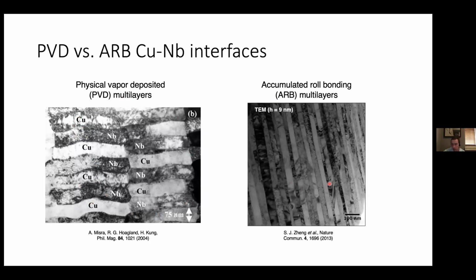And here on the right, you see another TEM micrograph of another copper-niobium composite, again, a laminate. So the alternating layers here are copper, niobium, copper, niobium, copper, niobium. The difference is that while the one on the left was made by physical vapor deposition, the one on the right was made by accumulated roll bonding. Accumulated roll bonding is something you might be familiar with from the idea of making a katana, like a samurai sword, where they would flatten it out by hammering it, then fold it in half, flatten that out again, and fold it again. Basically you're stacking layers of material, rolling them out so that they're flat like dough, then cutting them, stacking them again, and rolling them out again. You do this over and over and over again.